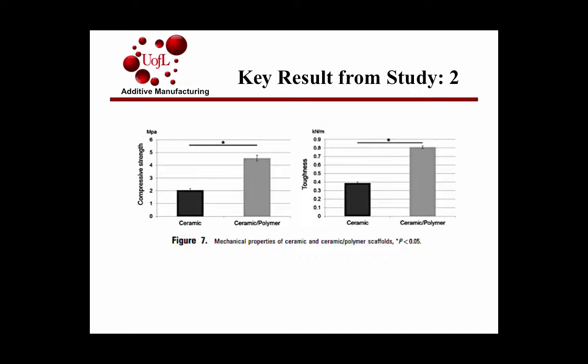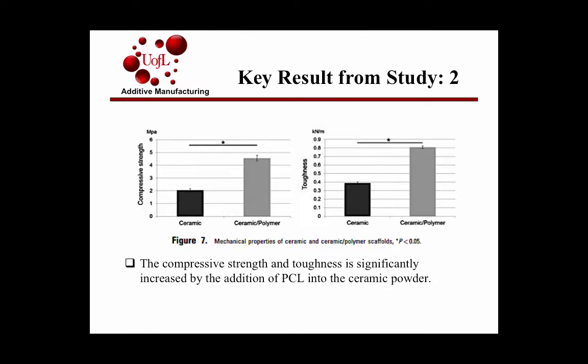And these parts were sintered at between 1300 and 1400 degrees Celsius. And the parts, just so you understand, we got a volume of 4.5 by 4.5 by 1.8 millimeters. And then they said that since they're using micro stereolithography, the largest that they could produce in surface area was 11 by 9 millimeters. So we're looking at really small, but we're also looking at really, really small compressive strength. But they concluded the addition of PCL into the ceramic powder significantly affected your compressive strength and your toughness. So it was a good thing to add into the ceramic powder.